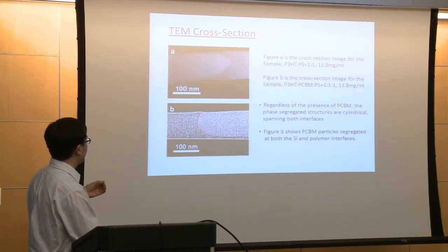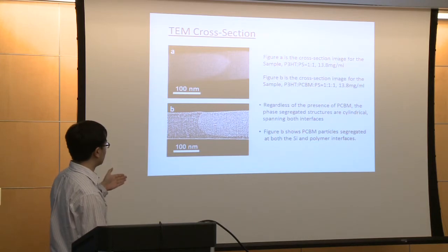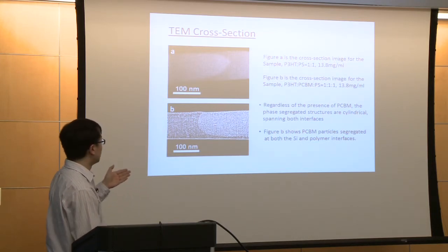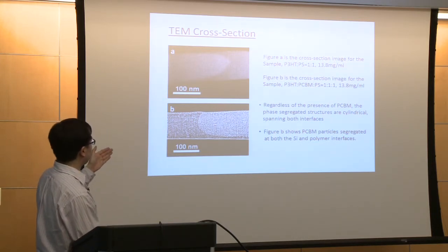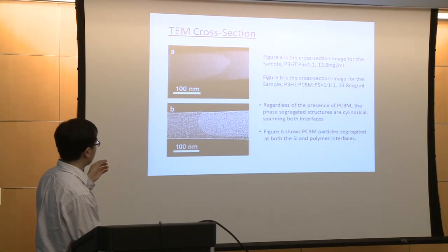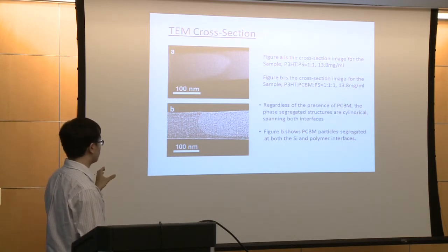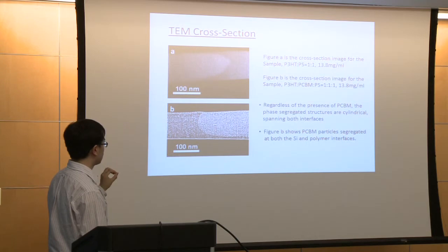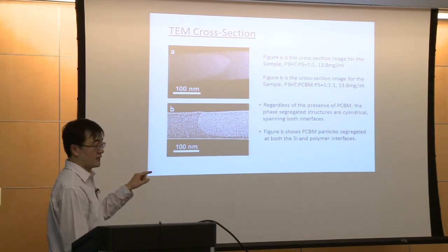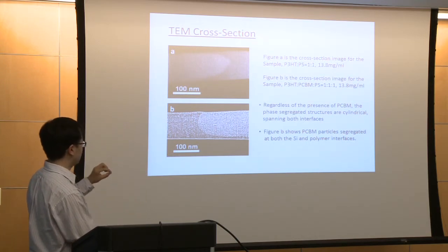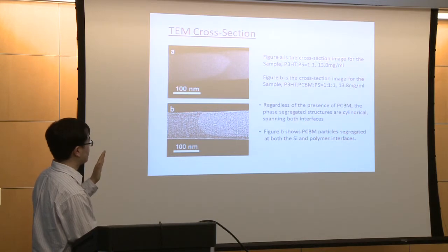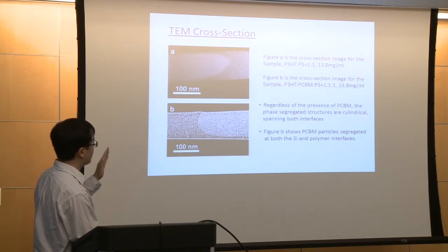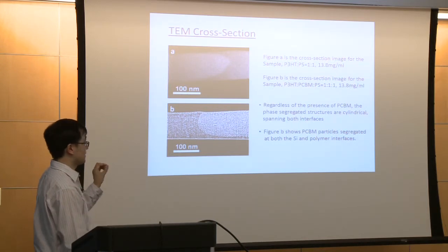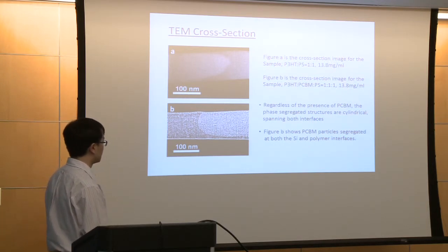And you can also find that the boundary for the sample with PCBM is much clearer than the sample without PCBM. If you enlarge the picture, you can see many dark dots along the polymer interface and the interface of the silicon and the polymer, which means the PCBM could segregate at the polymer interface and also segregate at the interface between the silicon and the polymer.